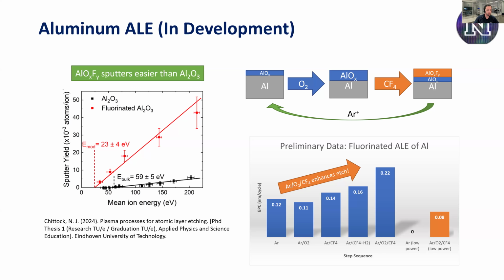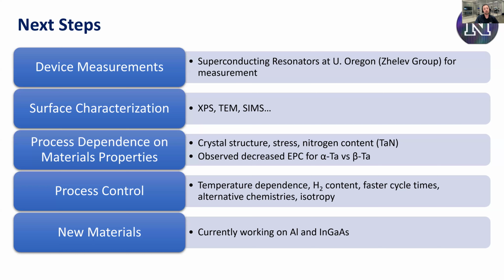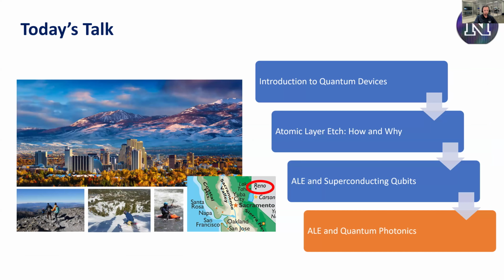Over the last couple of weeks, we've begun using lower ICP power and optimizing this a little bit more. You can see that we were able to get our physical etch rate to essentially 0. We don't see any etch. Then when we put the chemistry back in with that same amount of bias and everything else, we see the etch again. So this is a process that we're pretty excited about, that we think could have applications for qubits. There's a ton of work to do with this, but I don't want to bore you with all that. We'll be doing it over and over for a long time.